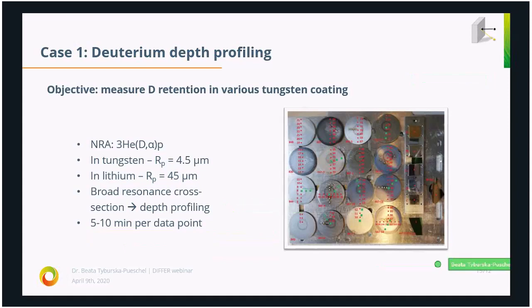As an example, here you have samples from Henny, which are tungsten samples on various substrates. Those red points are different data points on different samples. Then we also have green data points, which have been measured at our facility. The red ones were measured at IPP Garching. All in all, there are about 100 data points here, and I think I measured all of that within one day. This is how fast this technique is.